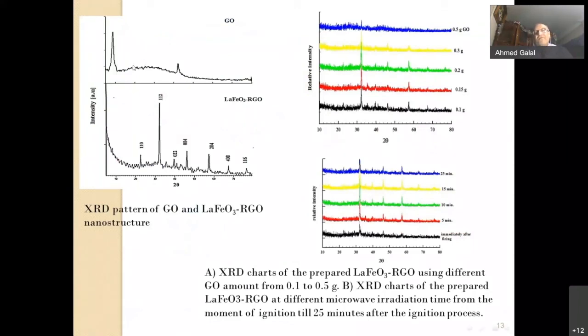We have confirmed the formation of the reduced graphene oxide from the XRD pattern and the formation of the corresponding perovskite as well. This slide here shows you the effect of the amount of graphene oxide used as a fuel. And as you can see, the most important distinct peak here is being increased as the amount of graphene oxide is reduced, which means that the graphene oxide has to be stoichiometrically used in order to obtain the desired confirmed crystalline structure. Now, the effect of irradiation time has also been tested, and we have concluded that between 5 minutes and 25 minutes irradiation is completely enough to produce the perovskite, and we compared that to the firing of the corresponding perovskite.